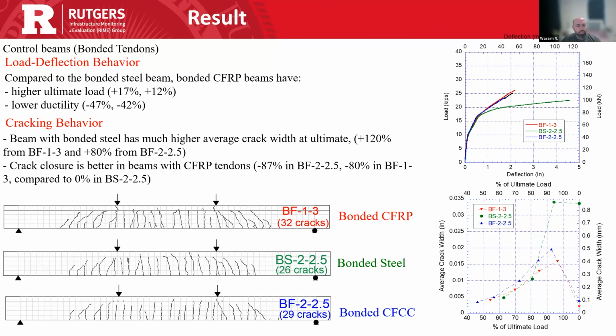As for the cracking behavior, beams pre-stressed with CFRP show better crack closure after the test is done. Because of the linear elastic behavior until failure in CFRP tendons, because they do not yield, that elastic behavior could close the gaps caused by the cracks. And that's shown here. If you see in the corner, there's a huge drop in the average crack width in the two beams pre-stressed with FRP tendons as opposed to that pre-stressed with the steel, where there is almost no drop in the crack width after the test is concluded.